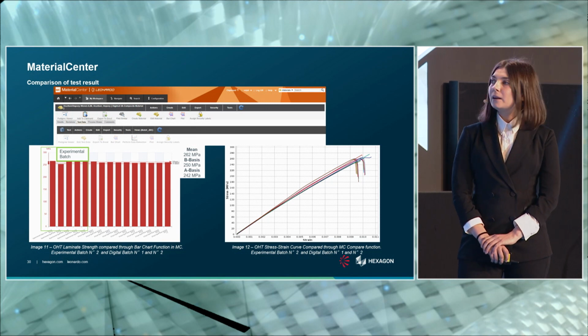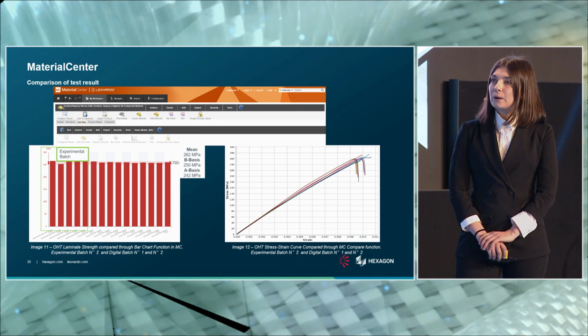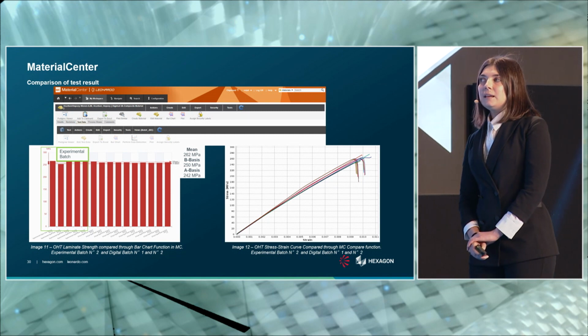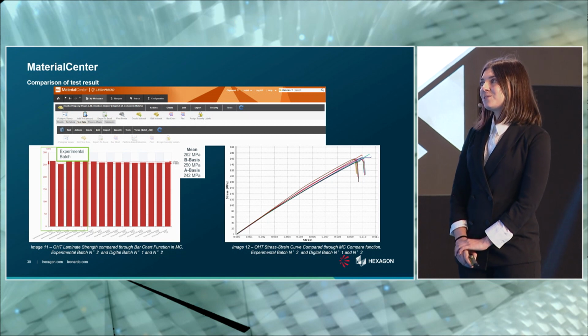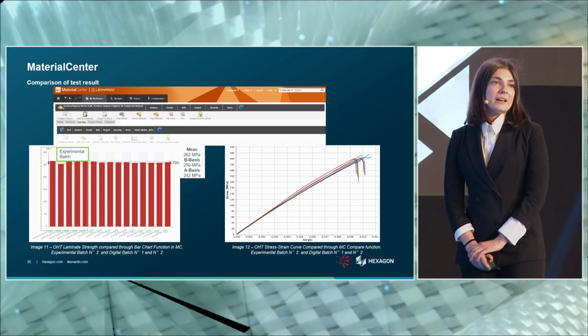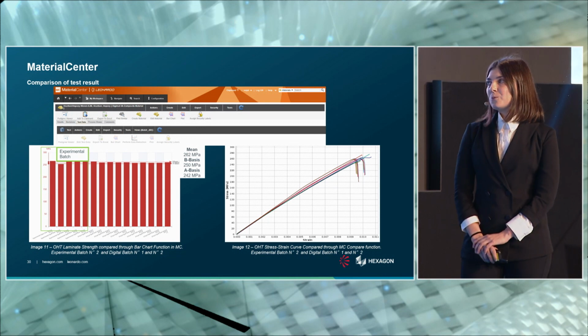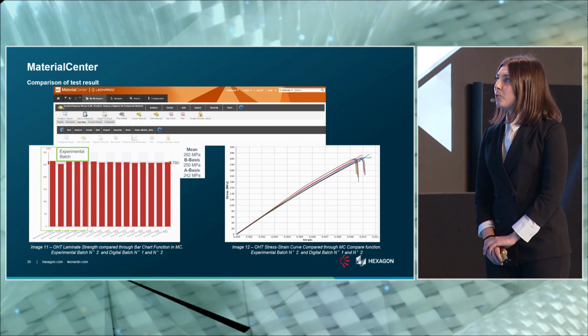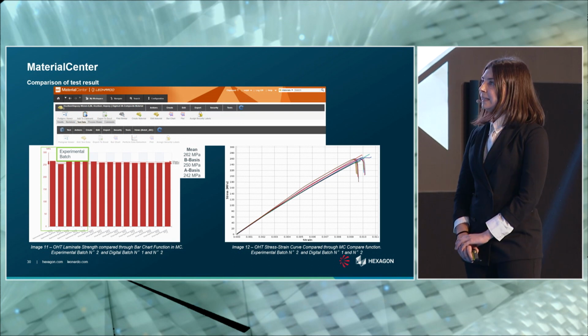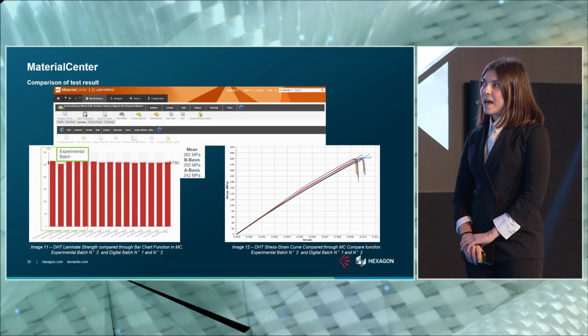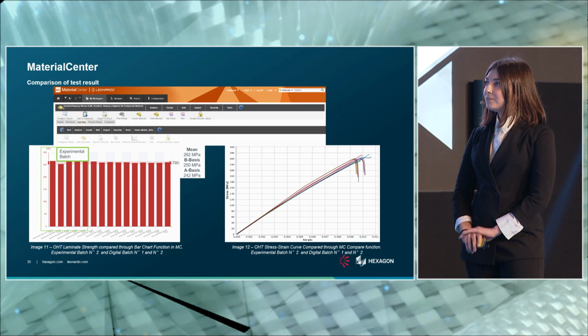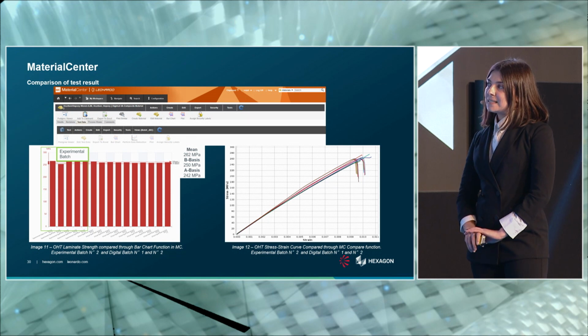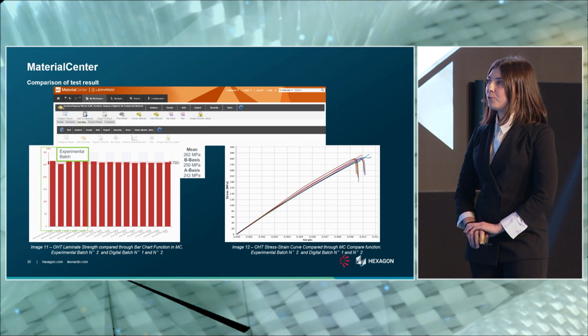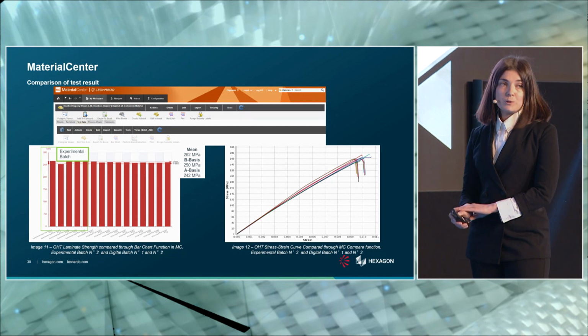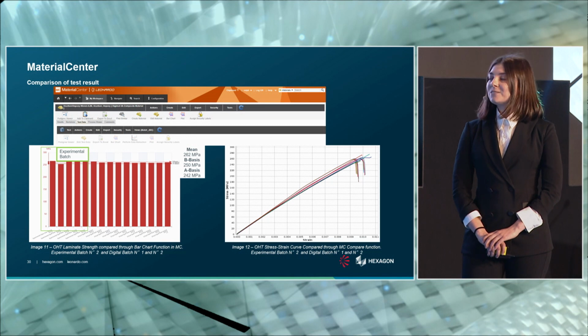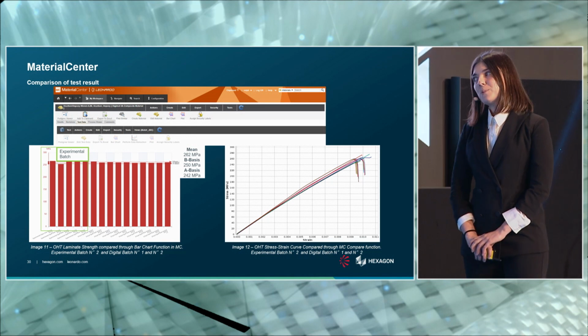The same analysis that we have made with a spreadsheet could be made with the aid of MaterialCenter. And as we can see, we can calculate the mean OHT laminate strength, the B basis, and the A basis. And on the right side, we have a very powerful diagram, because in this diagram we have 5 stress strain curves from experimental analysis and 10 stress strain curves from the virtual analysis. And as we can see, the virtual stress strain curves fit the experimental ones very well.